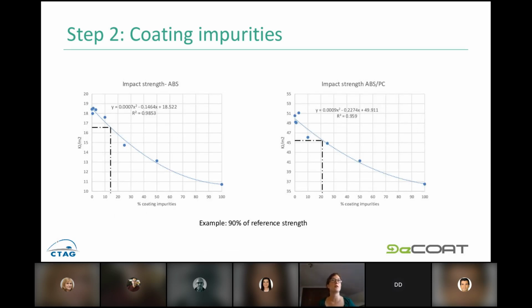Regarding the impact strength, as in the recycling studies, we see that there is an impact. If you increase the amount of coating impurities, you decrease the impact strength. And it's quite clear in those graphs that after 3% of coating impurities, there is a significant loss in properties. For example, in the graphs, if we want to keep 90% of the reference strength, it means that for ABS, we need to remove at least 90% of the coating impurities. And for ABS-PC, we need to remove at least 80% of the coating. So this is a measure of the needed efficiency for the debonding systems. We need to remove almost all the coating at the end of life.